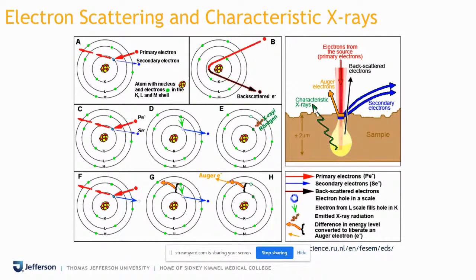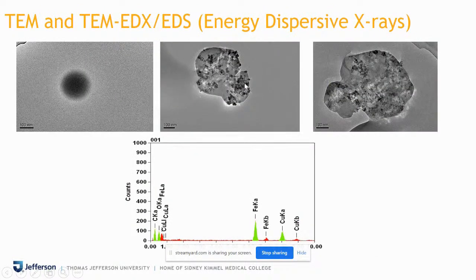So to confirm the Fe presence in these nanoparticles, our hypothesis was that when they self-assemble, the Fe particle would go inside the polymeric shell. Since it's present inside, the characteristic X-ray, which comes out from a depth of approximately 2 micrometer from a material, would be ideal confirmation that Fe is present inside the nanoparticles. So we performed transmission electron microscopy, where unlike SEM, the electron goes through the material, to measure these characteristic X-rays and see the internal structure of the